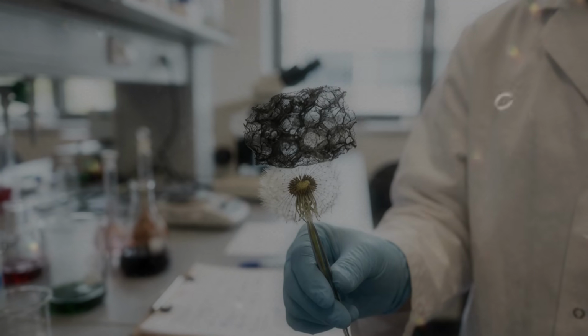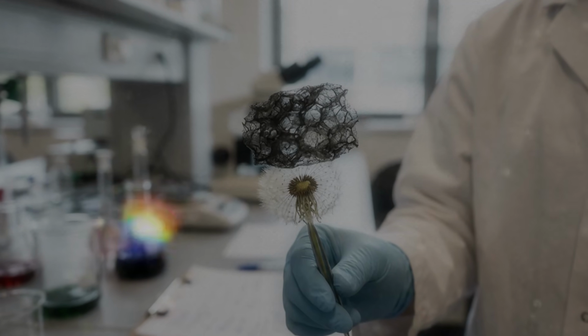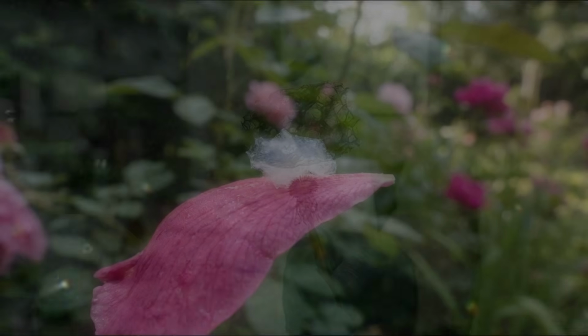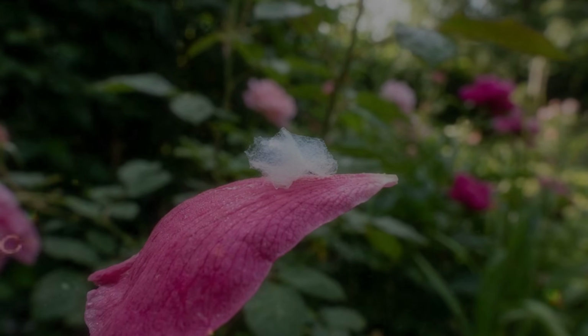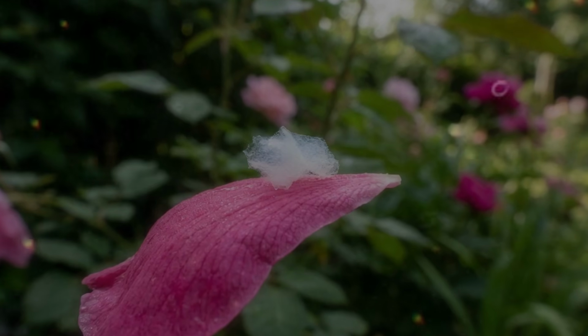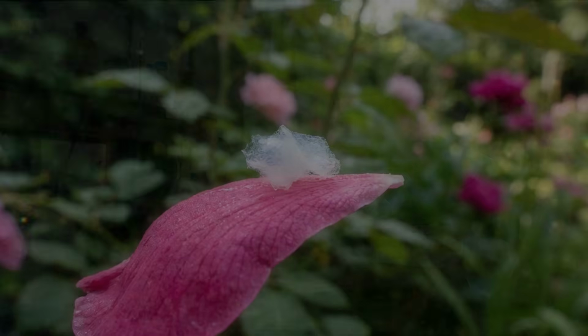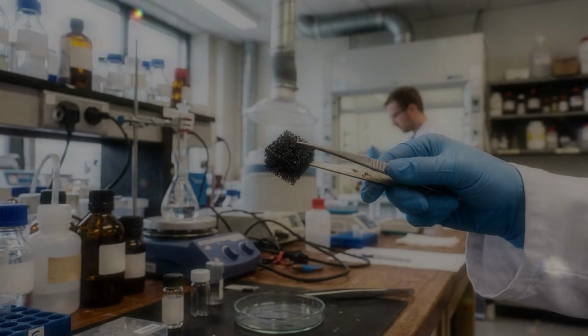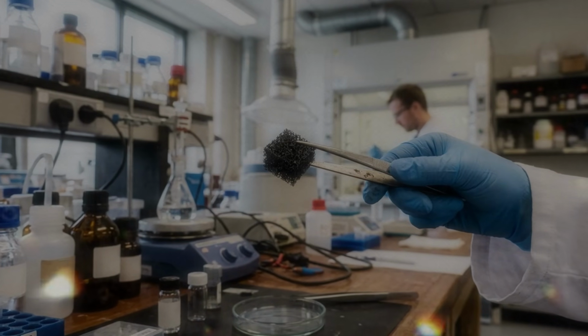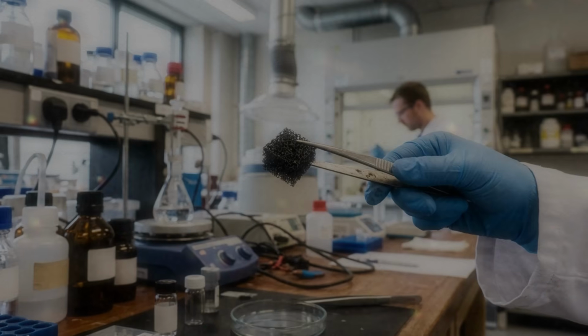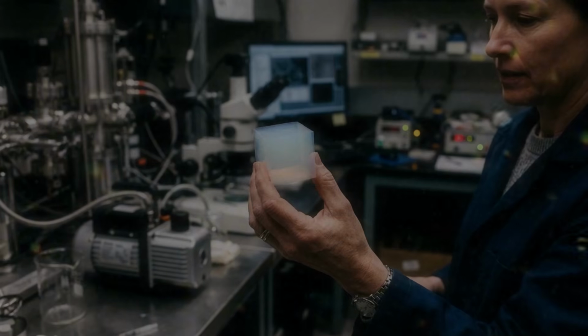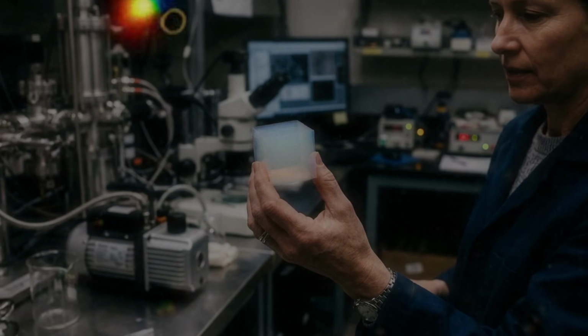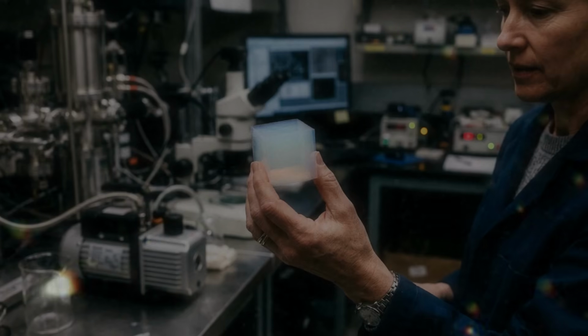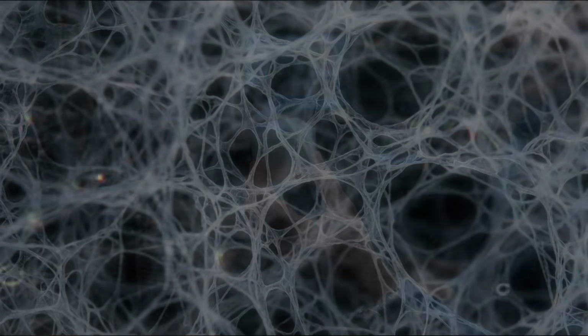Templates can produce regular openings. Additives can prevent sheets from stacking too closely. Stacking is a constant concern in graphene-based structures. Flat sheets naturally attract one another. When they come together face to face, they can form dense layers. The space between them becomes inaccessible. Surface area falls, pores disappear, and the material becomes heavier for its size.